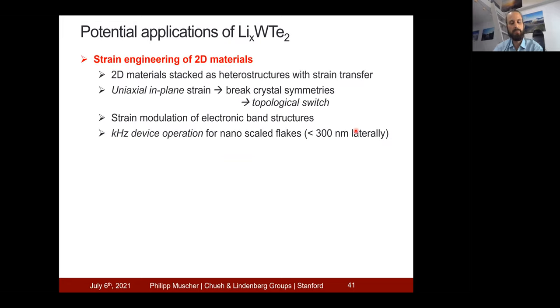So potential applications of tungsten ditelluride with lithium insertion are in the field of actuation. We can use this property for strain engineering of 2D materials. You can take one 2D material and stack another 2D material on top of it. As one of them will be strained, that strain will be transferred to the other one. The uniaxial in-plane strain that we are observing can break crystal symmetries of the other material that's stacked on top of it. And this symmetry breaking could be used as a topological switch to switch the quantum properties of topological materials. Also, the strain modulation in that type of system tunes the electronic band structures of 2D materials.